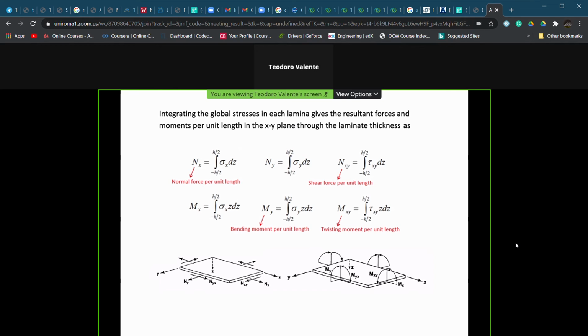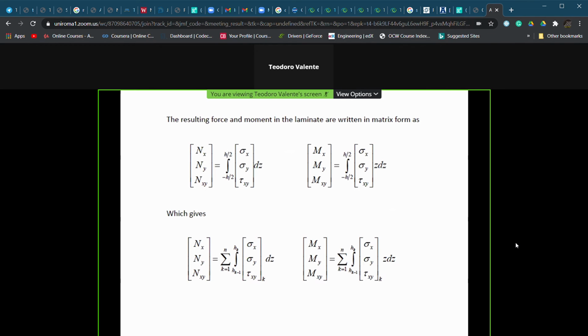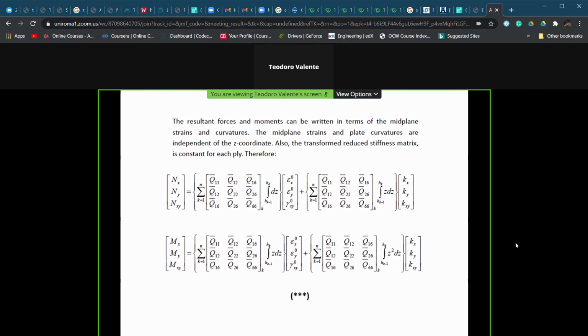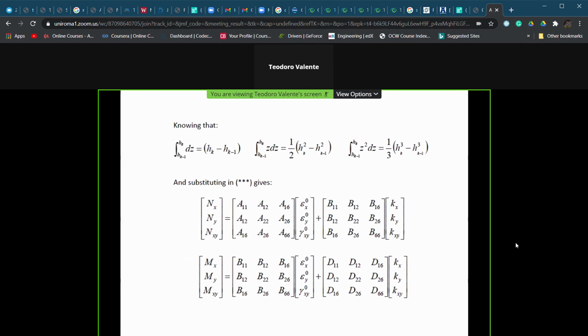From the evaluation of the strain, we can make the integral, so we can make also an evaluation of the forces and the moments which are present inside the single lamina. And so we can write also our expression in terms of finite quantities, that is by using the integral inside the single lamina and the single ply. Ply and lamina are synonymous in this case, to have an idea of the resulting capabilities in terms of supporting applied loads by the laminate. So that's classical construction science, something that you have seen some years ago by other colleagues with respect to myself.